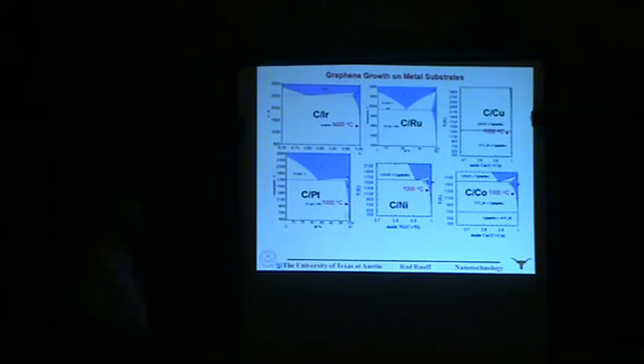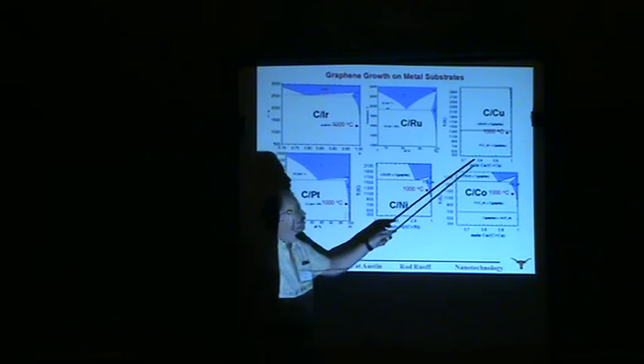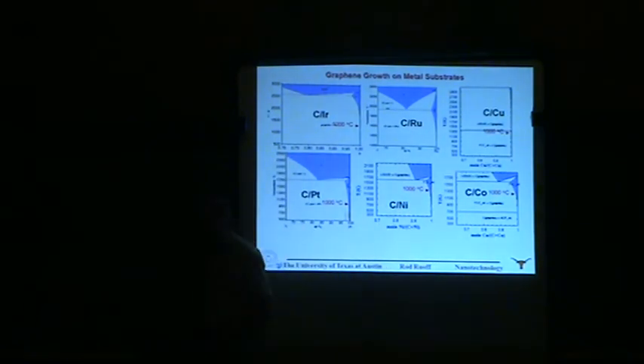So for example, if we consider processing at 1,000 degrees C, you can see for some of the systems like platinum and nickel that the solubility of carbon in those metals is quite high at thermodynamic equilibrium. In nickel at 1,000 degrees C, it's 1 atomic percent. So there's a large amount of carbon actually in the nickel at equilibrium. But in copper, the solubility is very low, and I would argue it might even be 0 in data that I will show you. But there are several papers in the literature that talk about the solubility being a few parts per million or about 150 parts per million at 1,000 degrees Celsius.